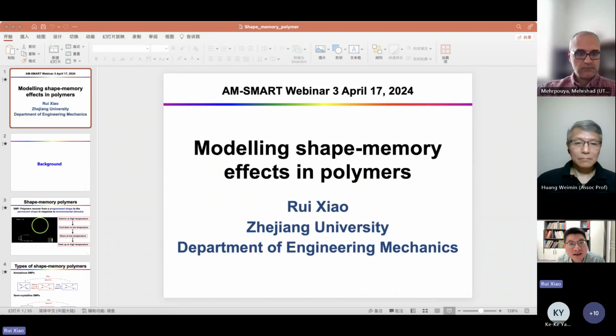If you have this effect, you can design something called multiple shape memory effect. The idea is you have a permanent shape. You program one temporary shape, cool down, and program a second temporary shape, then cool down again to fix this shape. When it recovers, it will recover to this shape first, then to the final permanent shape. The mechanism is straightforward: since you have temperature memory effect, if the two programming temperatures have well-separated recovery regions, you can get multiple memory effect.